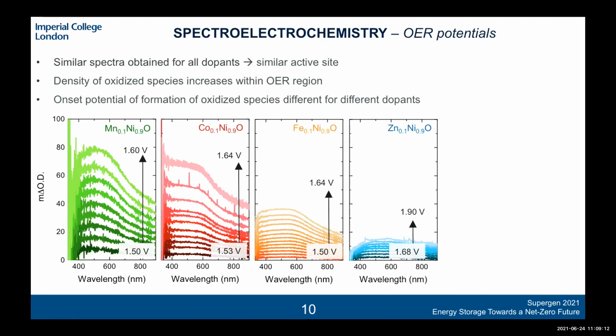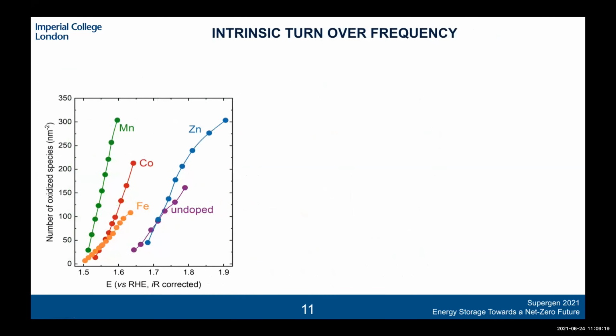We can take all of this analysis one step forward, and I won't go into the details of how exactly we do it, but you can convert this data into a quantitative density of oxidized species as a function of potential. And like we've seen before, in the case of manganese, you have these species forming at a much lower potential compared to the zinc and the undoped oxide.